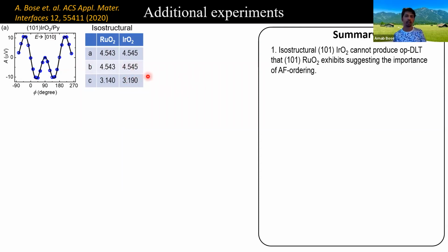So it clearly suggests that only crystal structure and crystal symmetry is not enough for these extraordinary spin currents. We need this magnetic ordering that ruthenium dioxide exhibits, but not iridium dioxide. However, this iridium dioxide is also a very interesting material because it also hosts Dirac nodal lines that can create an anisotropic spin Hall effect, which we reported in our previous works. For more details, you can check out this paper.